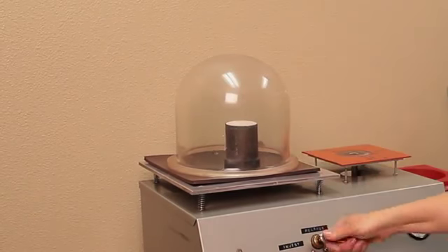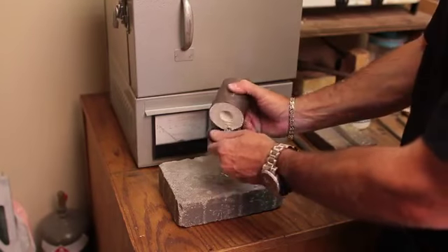The reason for this is that some air can get into the investment during the pouring. The bubbling you see is the air being removed from the investment. After the second vacuum is done, the investment is left to dry and harden. This takes approximately 1.5 to 2 hours.